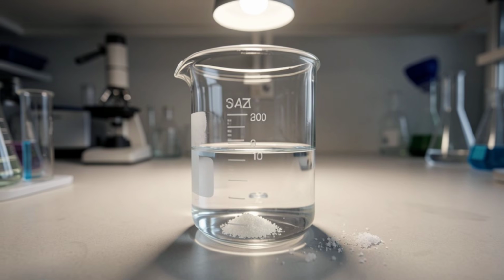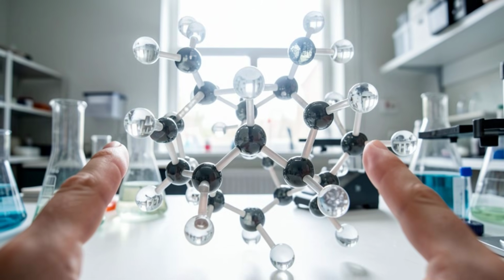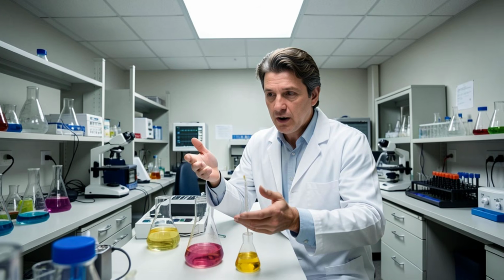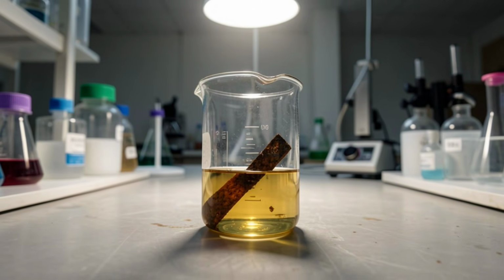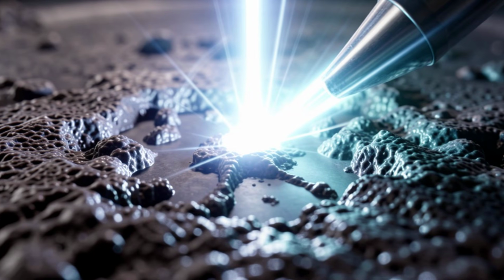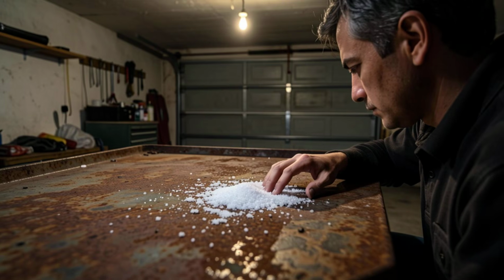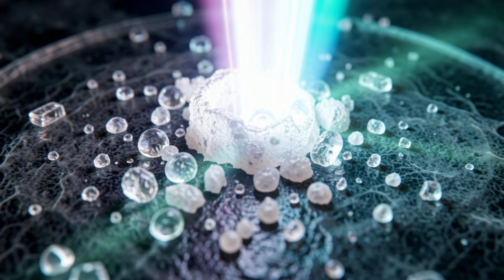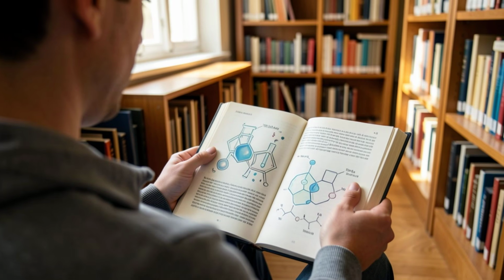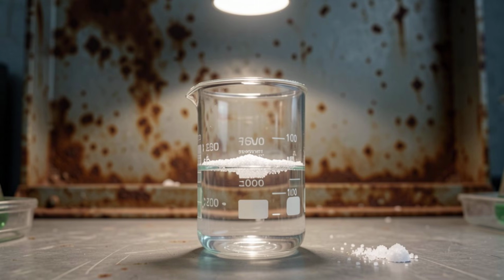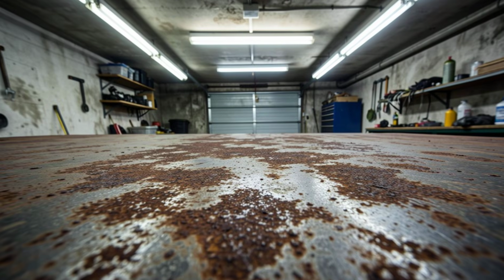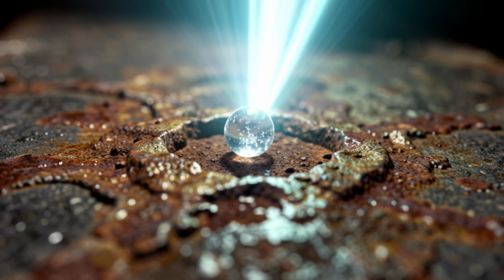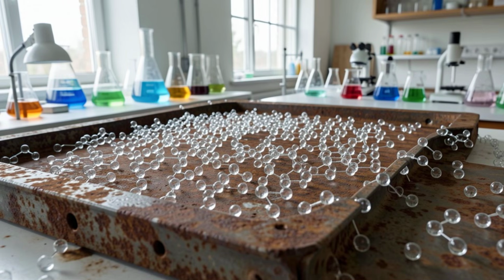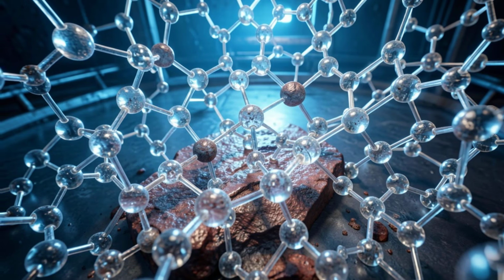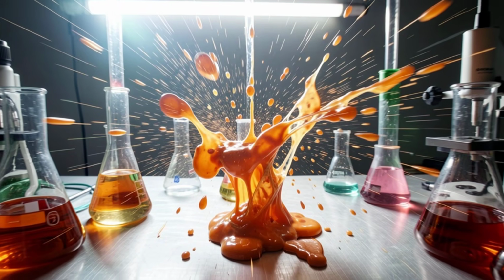Here is where the salt changes everything completely. When you dissolve sodium chloride into the acetic acid solution, the sodium chloride dissociates completely into sodium ions and chloride ions. The chloride ions are the operative component in what chemists describe as halide-assisted dissolution of passive oxide films. The chloride ion has an extremely high affinity for iron, and it attacks the passivation layer on the rust surface through a process of competitive adsorption, essentially displacing the oxygen-containing compounds that give the rust crust its passive acid-resistant character. Once the chloride ions have broken down that passivation layer, the acetic acid molecules now have direct access to the reactive iron oxide matrix beneath, and the dissolution reaction accelerates dramatically.